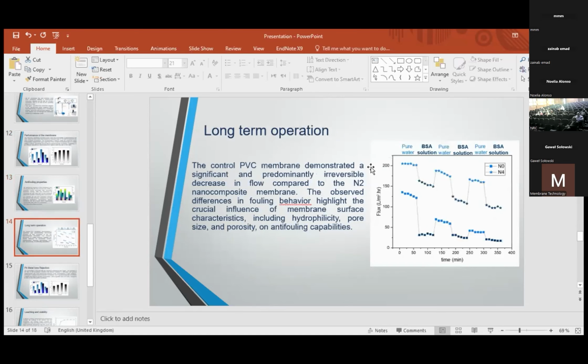To evaluate the long-term operation of the optimized membrane, 3 cycles of extended filtration tests were conducted for both bare PVC N0 and N2 nanocomposite membrane. As illustrated in this figure, these tests aimed to evaluate the stability and the longevity of the produced nanocomposite membrane over a 6-hour operation period. During each cycle, the process included measuring the flux rate of pure water for 60 minutes, assessing the decrease in flow rate using a BSA solution for another 60 minutes.